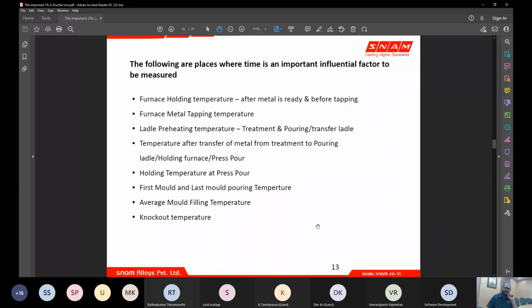So you suddenly get a sulfur increase in your liquid metal, and you will be surprised to see how the sulfur increased from the furnace to the final pouring. This sulfur, which is not accounted for or measured, can get into the liquid metal again because of the very high ladle preheating temperature. Because of this, the increase in sulfur can be small or localized, which can affect your magnesium recovery and your entire properties. So care must be taken that we do not preheat the ladle to a very high extent.